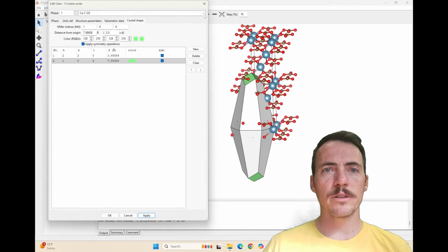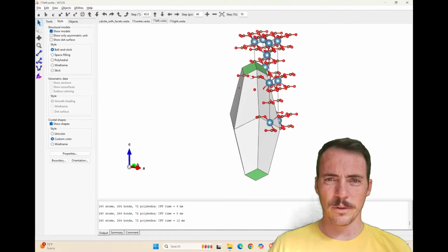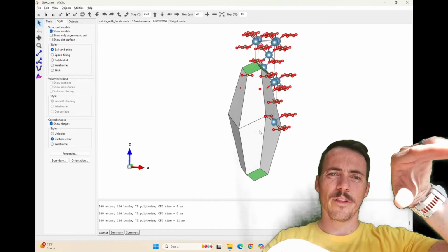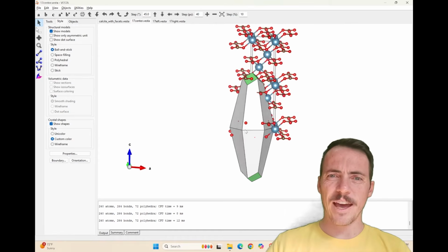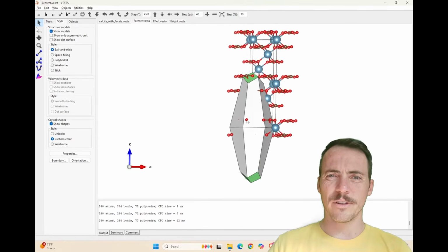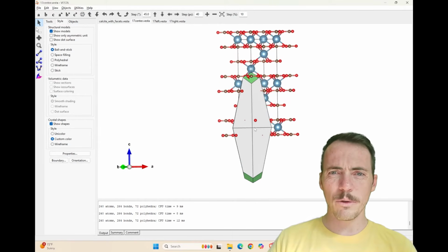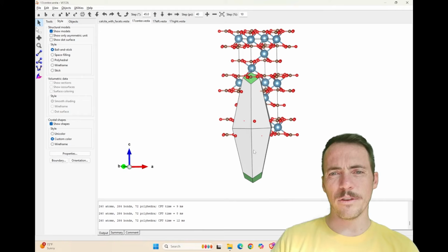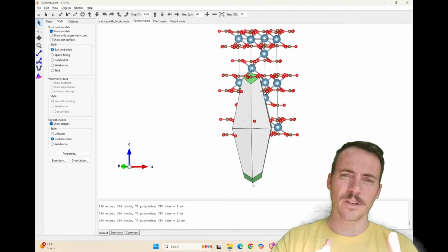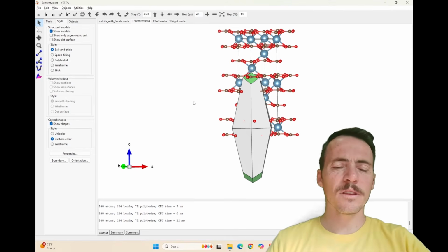Now notice how it looks different. It looks very similar to the one before, right? Quite similar. So here's the left one. These top and bottom rhombohedron facets are sort of opposite from one another. And in the center, they're doing the same thing, except we have this flat equatorial line, right? Slightly different. Now, if this was a twin structure, how would it look different? If it was twinned, it would preserve mirror symmetry, meaning this green rhombohedral facet would be oriented the exact same way on the other side of that twin boundary. But it's not here. It's clearly not. It's shifted, right?